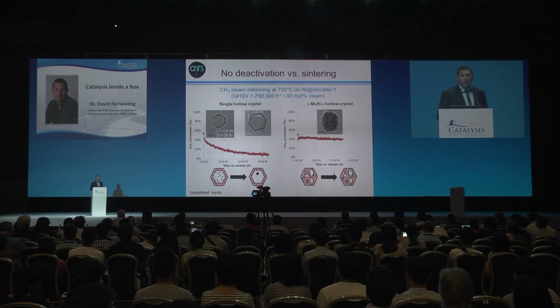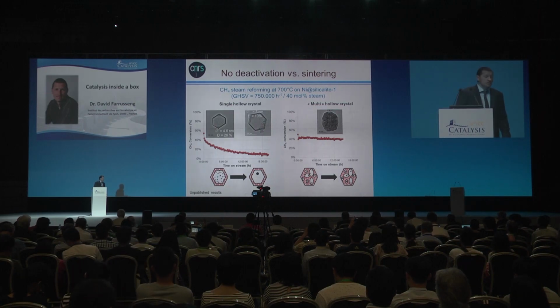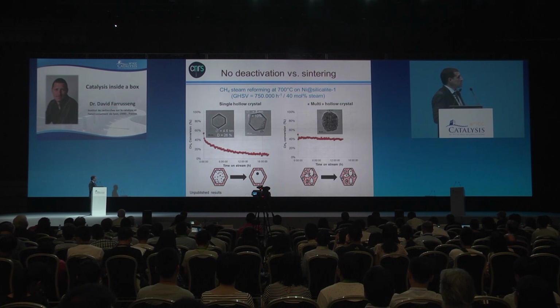So we selected the steam reforming of methane in very harsh conditions, 700 degrees C here on the nickel silicalite, with 40% of steam. It's really huge. And look at here the velocity, 750,000 per hour. It's a huge velocity. Here you can see the methane conversion as a function of the time on stream. You can see an exponential decay, which is due to the sintering of the nickel particles.